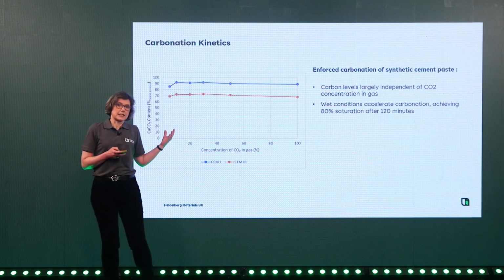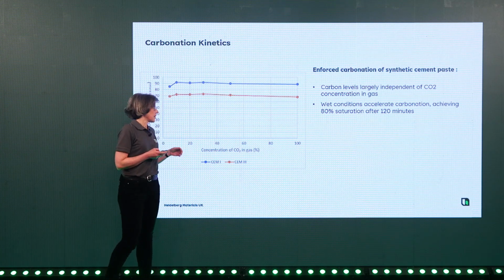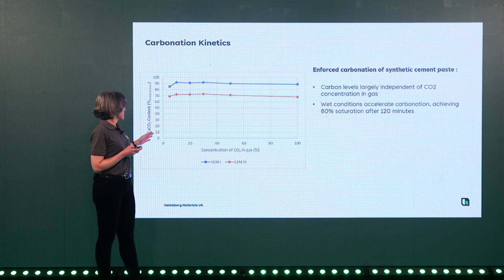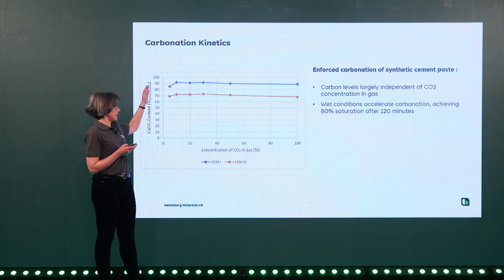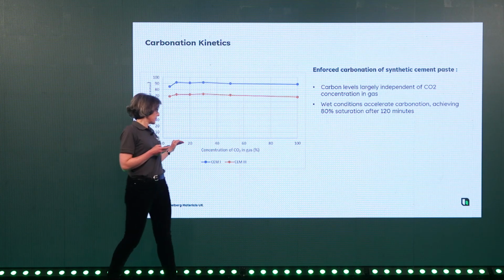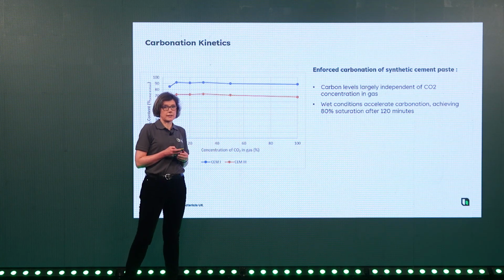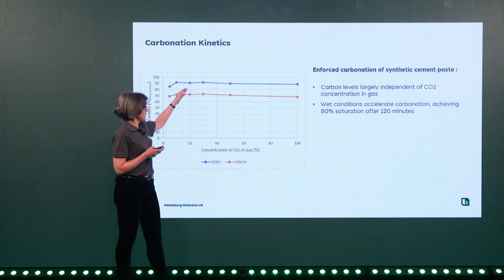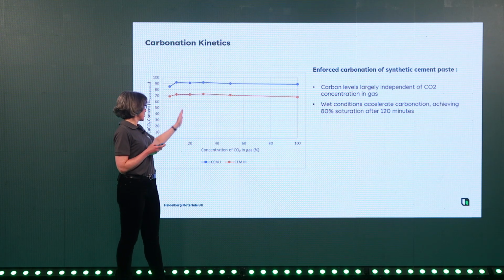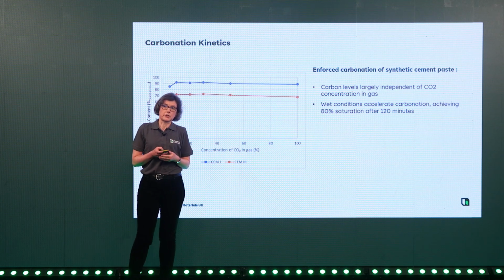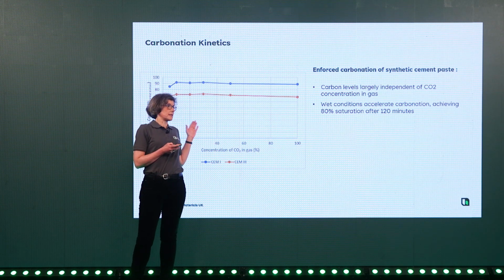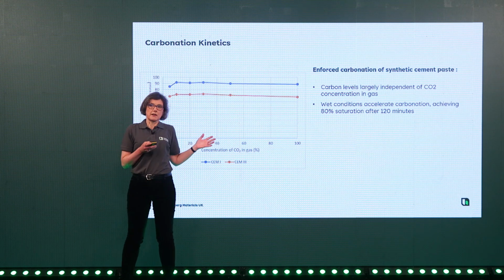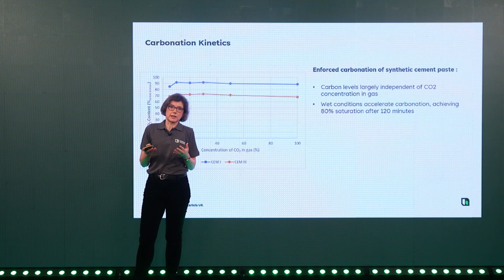Looking now at the kinetics behind carbonating paste, what you see here is the level to which RCP has been carbonated under different levels of CO2 concentrations in the gas. And what you see is that after 120 minutes, even at low concentrations, as long as it's about 10%, we almost saturate the RCP with CO2. This is an important finding because it means we can be using almost any gas which contains CO2. It doesn't matter how highly concentrated it is in the gas.